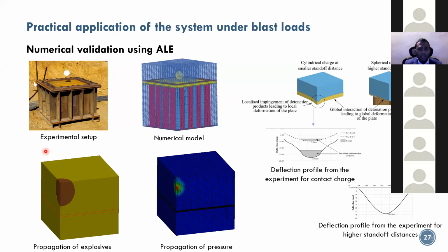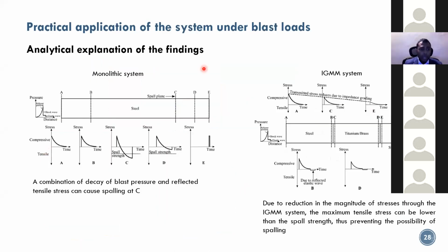So what this system does, IGMM, is the impedance graded multimetallic system. What this allows you to do, compared to only having a single material, is what's called attenuating. That is, we are reducing the magnitude of the stresses that get transmitted. So when you create barriers in a system, you can reduce the stress that gets transmitted. By doing that, we are preventing any major kind of failure.